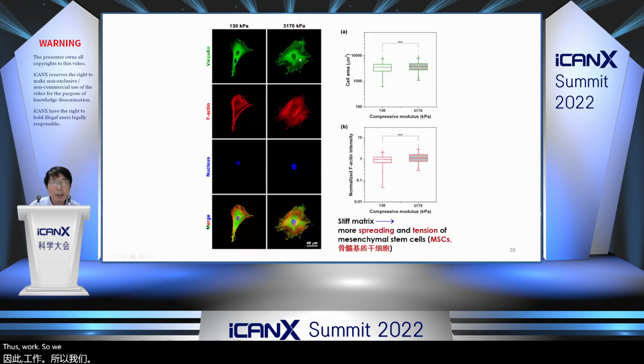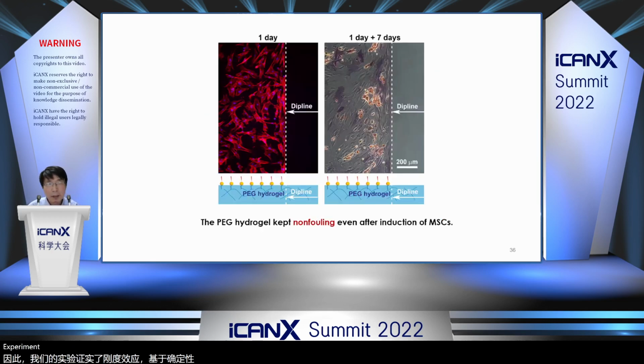So here is a fluorescence micrograph of the mesenchymal stem cells. According to our statistics, we did find more spreading and tension of mesenchymal stem cells. So our experiment confirmed the stiffness effect based on a deterministic experiment. However, it is only for cell adhesion. If one would like to examine cell differentiation, it is much more challenging because cell differentiation cannot be finished within one day. However, the proteins in the serum will very probably adsorb on the surface. So an ideal surface should resist non-specific protein adsorption for quite a few days.